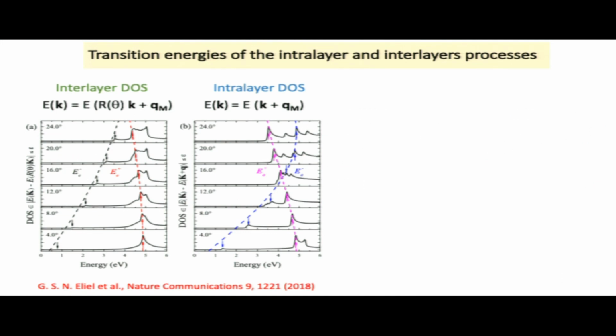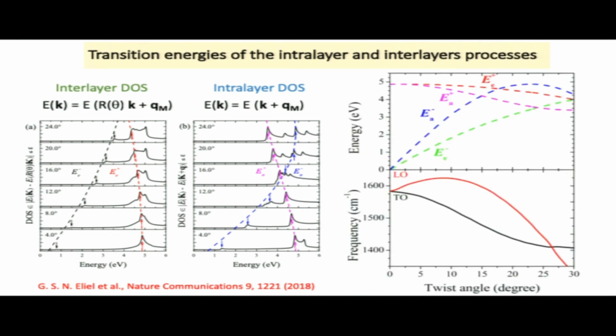Okay, this was the calculation of the energies for the intralayer and the interlayer process. This I can explain in detail after. We have here the transitions of the interlayer and the intralayer process. In fact, we have two for each case. And here is the energy of the interlayer process as a function of the angle from 0 to 30 degrees. And here is the phonon dispersion of the LO and the TO band.